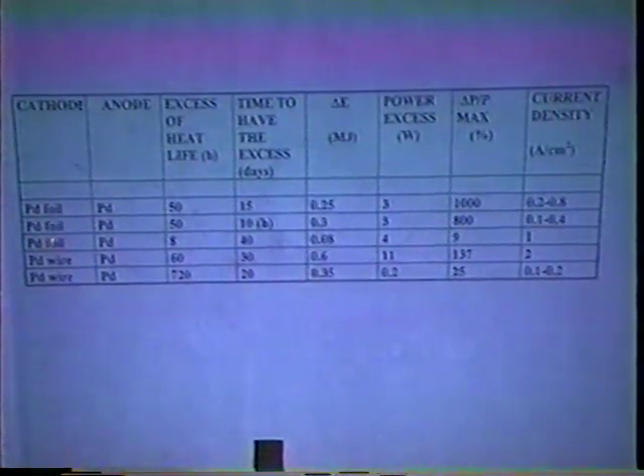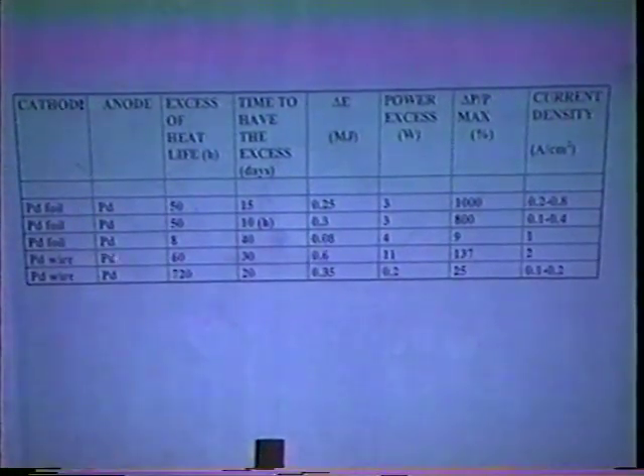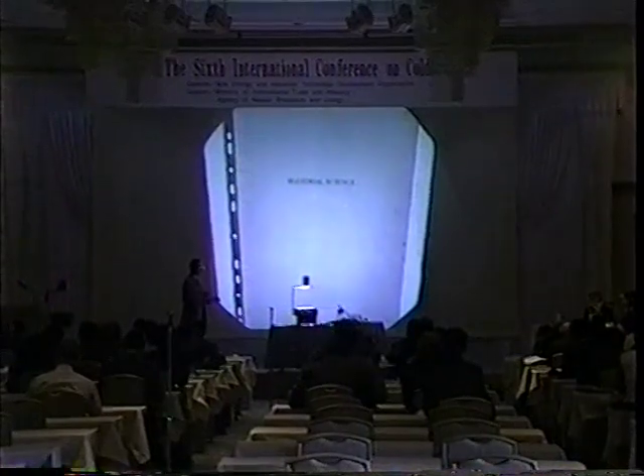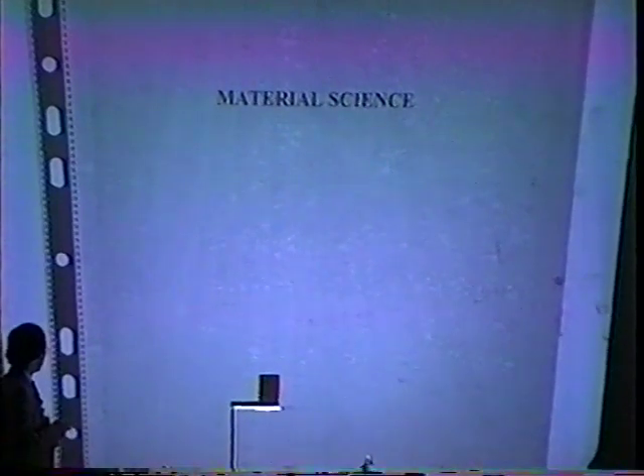What we discovered is that between these coils from one batch and this other one from another batch, there is a substantial difference, because we checked the solubility of hydrogen in this batch, and we discovered that the solubility is much higher than in this one. And we correlated this effect with the microstructure of the metal, which in this case was very different. Then we decided to start with a study of material science to understand what is the real inhibition inside the material for having high loading ratios. So we decided to interrupt for some time the calorimetric measurements and to start with loading study.